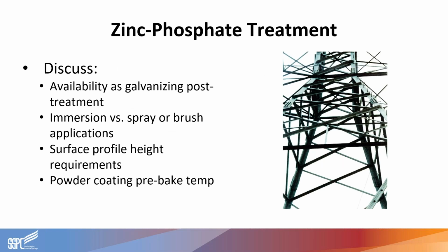Another method for profiling the galvanized surface is to passivate the surface with a zinc phosphate solution. We kind of touched on this before. So this solution, it reacts with zinc metal on the surface, and you get a layer of zinc compounds that are tightly bonded to the surface, protect from oxidation, and you also get a roughened surface out of that, which you can paint or powder coat over.